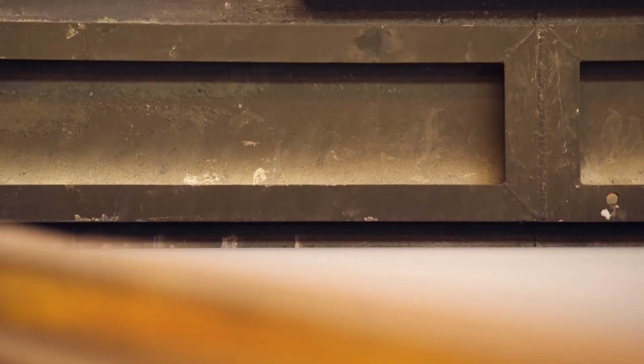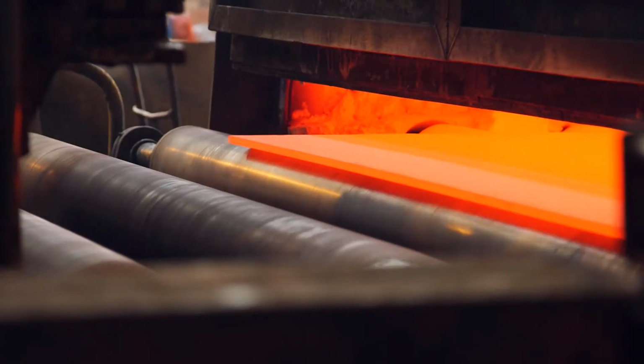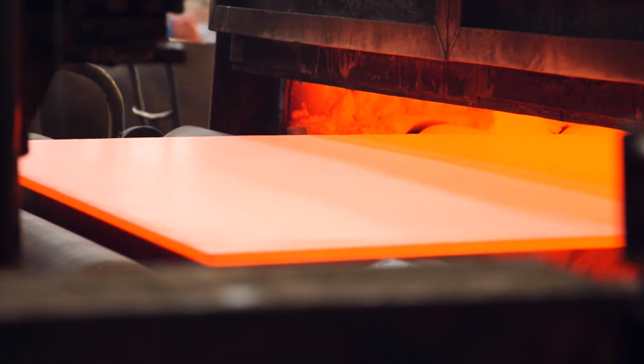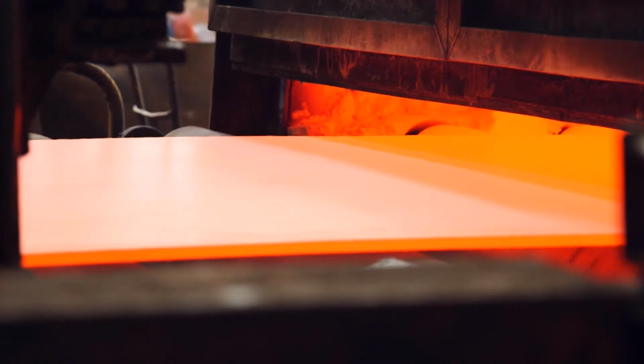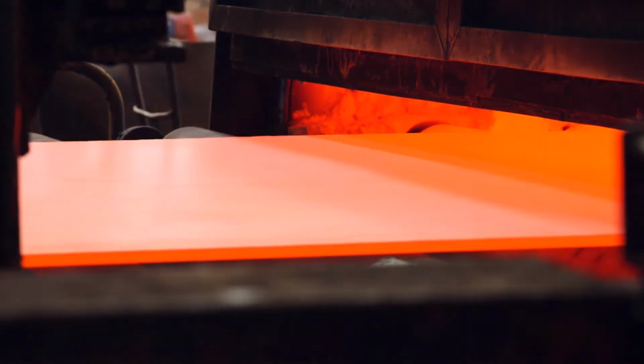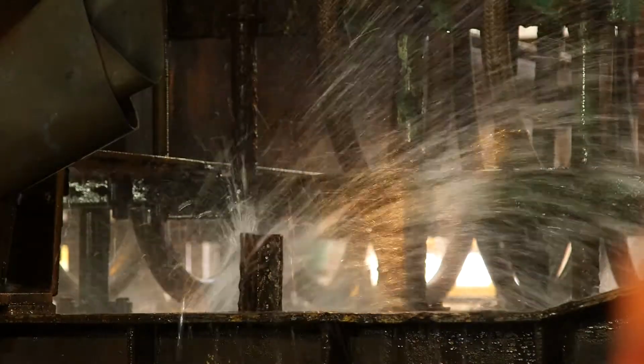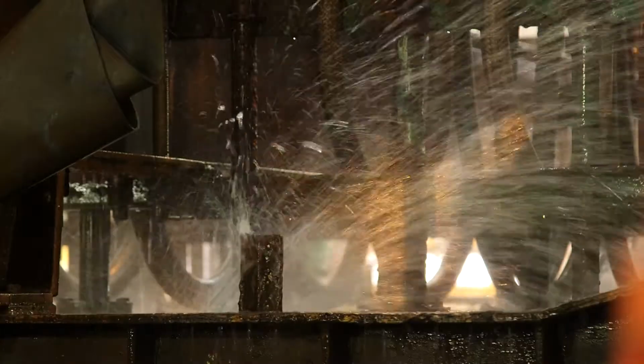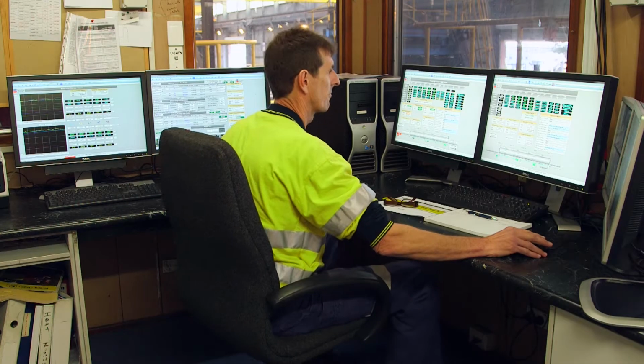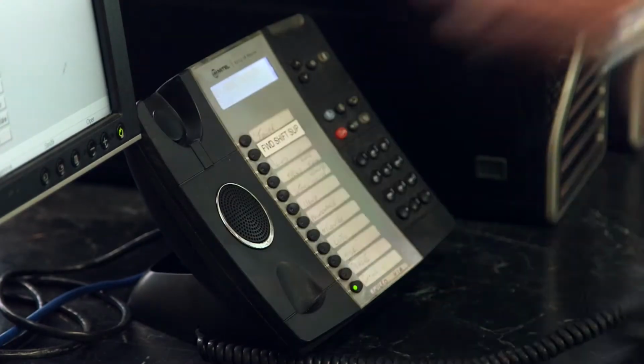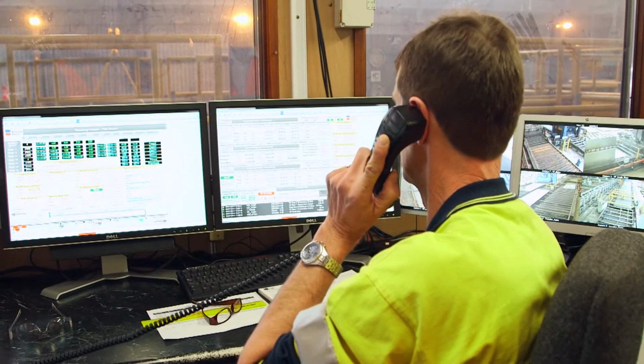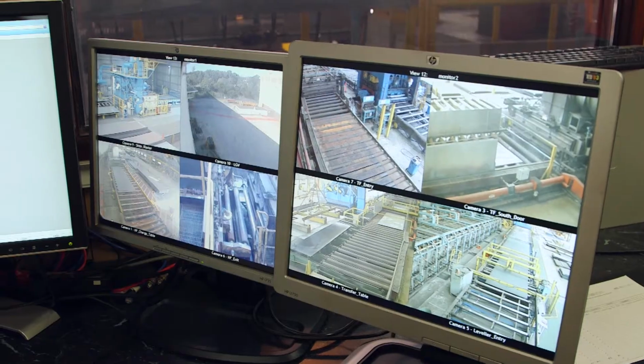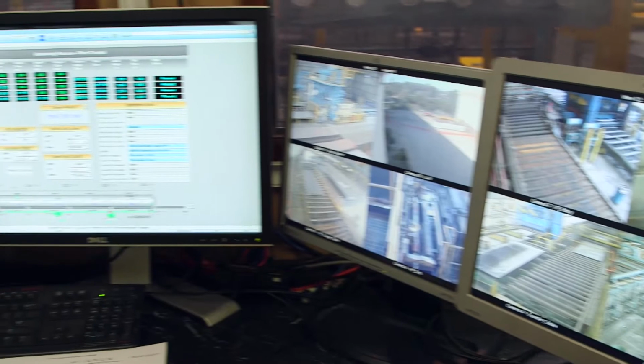After exiting the hardening furnace, the plates are quenched with cooled water. The quenching, as the name implies, involves cooling the plate extremely rapidly from 900 degrees Celsius to just above room temperature using large volumes of high pressure water. Obtaining an even quench is essential to keeping the plates as flat as possible.